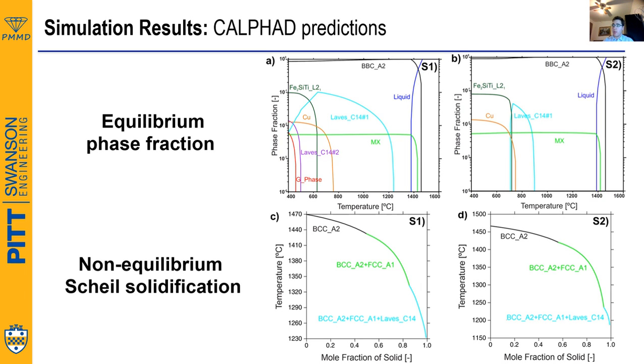If we now focus on the last two images, the non-equilibrium solidification behavior, we see that the predicted outcome is the same for both samples. The as-cast microstructure is expected to have the BCC ferrite accompanied with some amount of the MX, the FCC titanium carbide phase, and the unavoidable Laves phase is expected to be seen in the as-cast microstructure.